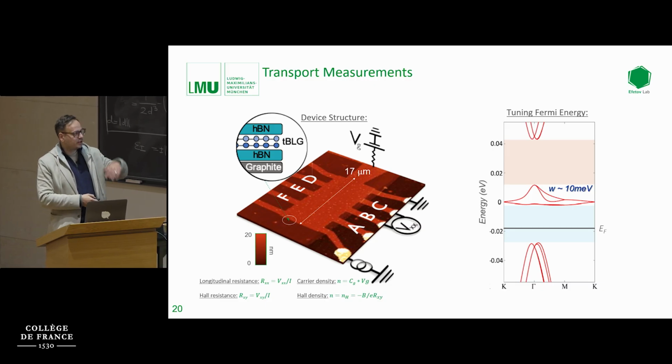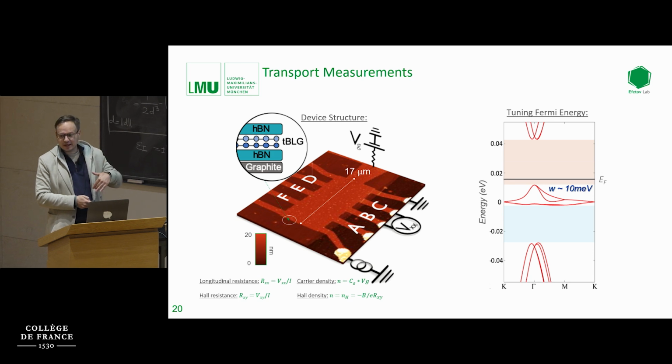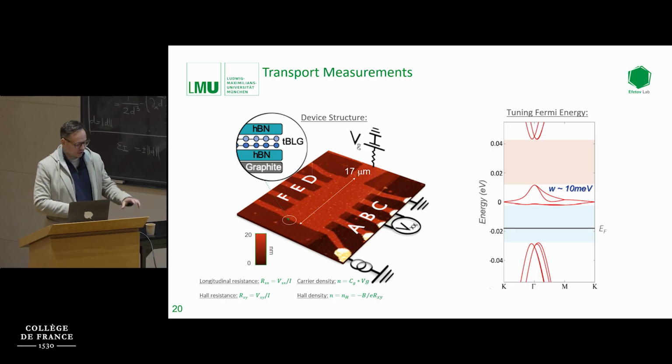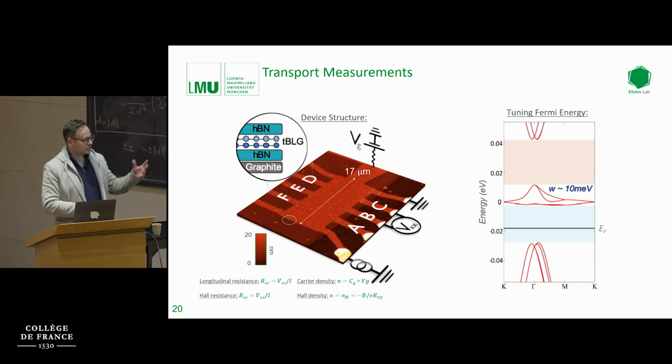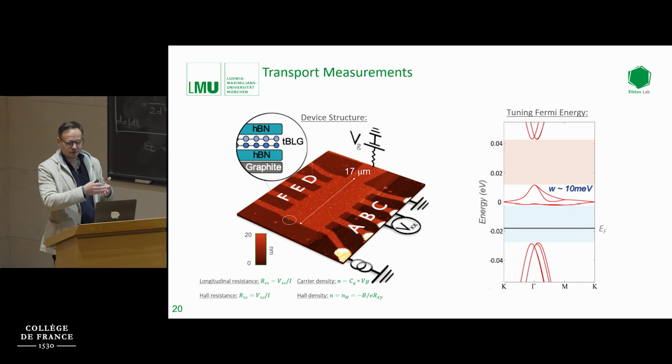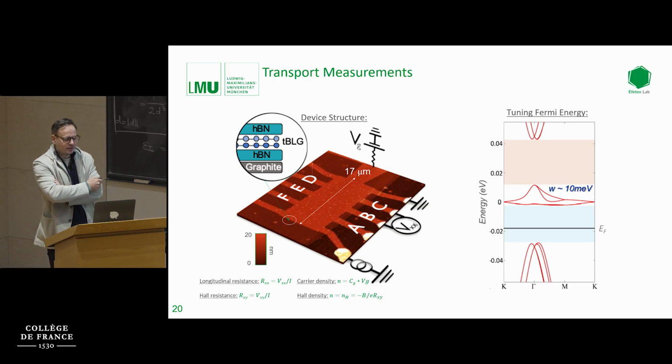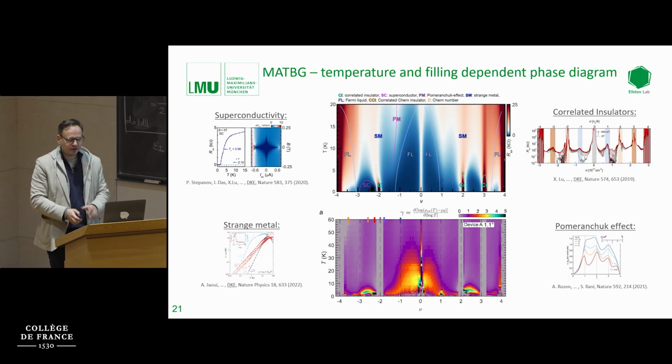So it allows us to completely fill and completely empty these flat bands and really take the entire phase diagram as a function of the Fermi energy of the system. Again, if you would do it with crystals, it would take you the growth of many crystals with various doping levels. Here, you can really use the tunability of these devices to create entire phase diagrams.